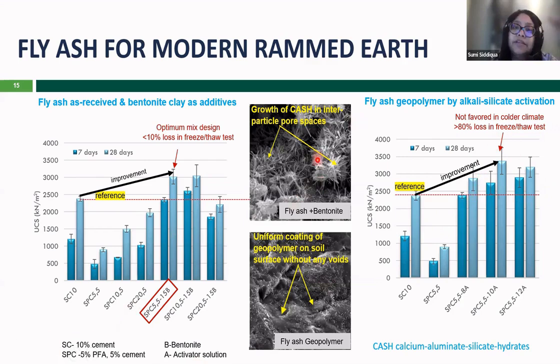Now, microstructure, we see the growth of CASH in the pore space, which is the calcium aluminate silicate hydrate. So that's what we see over here. This is the fly ash and bentonite, and the fly ash geopolymer. We see that uniform coating of the geopolymer on the soil surface without any void. So that's the impact of geopolymer.